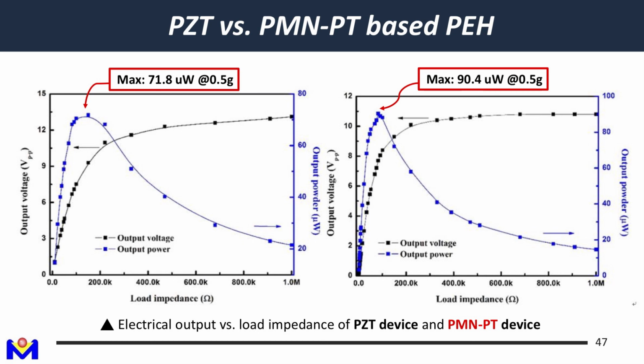In the beginning, we actually hoped PMN-PT could give us much better results because the piezoelectric constant of PMN-PT compared with PZT is much higher. That's also our general impression. But the problem is the dielectric constant is also much higher. The figure of merit, we recall, is d squared over epsilon. When you have a higher piezoelectric constant but also a higher dielectric constant, the overall figure of merit is not that good. So in the end, we actually gave up PMN-PT, although it can give us a little bit better performance. But the fabrication difficulty is higher than PZT.